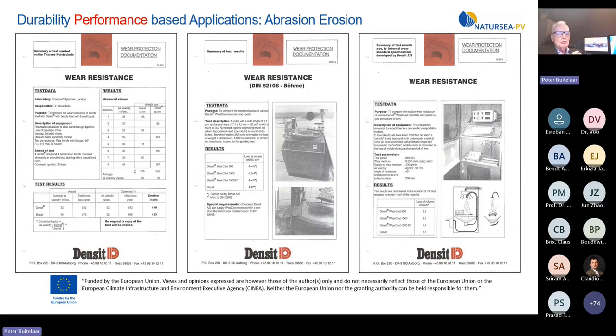Several standards and self-developed tests are used to test UHPC for wear protection, because the first commercial supplier of UHPC was not only 100% owned by a large cement producer, but also part of a very large industrial group supplying to the cement industry. This made real-life testing on sites possible, often with spectacular outcomes and a service life extension from sometimes days in normal steel to months or even several years.